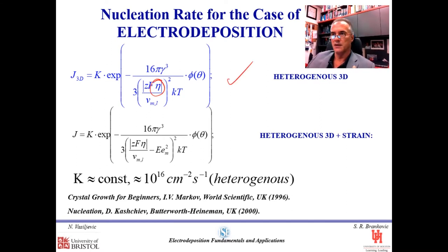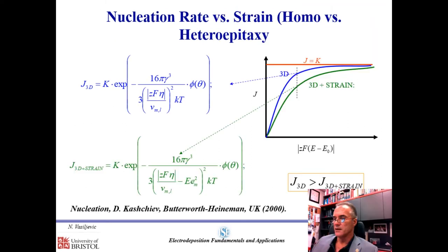However, if the substrate has a big misfit, let's say we are trying to deposit silver on platinum or ruthenium or something like that, then the strain in the nuclei starts to play an important role in the energetics of the nucleation, and generally the nucleation rate will be different for the same applied overpotential. Having said that, and just looking into the mathematical formulation, you could see that for the same overpotential that we apply, depending on whether the strain plays an important role or not, we can have quite a significant difference in nucleation rate. We should keep this in mind, because sometimes we could have way different results depositing the same material on two different substrates.